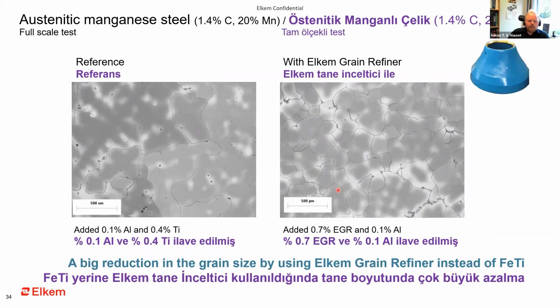Then we have a case with a 20% manganese steel. And this is the reference sample. You see the scale bar here is 500 micrometers. And you see these grains are huge. And the normal practice for this foundry was to add 0.1% aluminium and 0.4% titanium to the ladle just before casting.